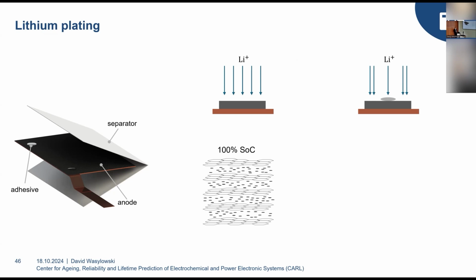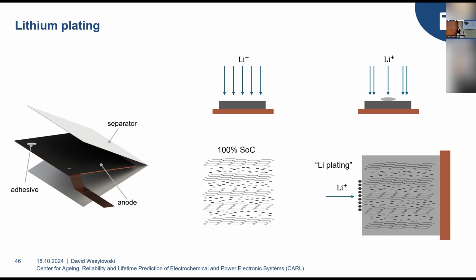But if we now have this inhomogeneity in this anode, which is blocking the lithium ion flow, causing a higher lithium ion flow at the edges of the adhesive, you can imagine that if the battery is not designed for this high current to happen at the perimeter of this adhesive, the lithium ions do not have the time that they need to place themselves into the anode, and then unfortunately have to be deposited on the surface of it. And we call this effect lithium plating, and there's a bunch of literature on why this is bad and why we should avoid this.